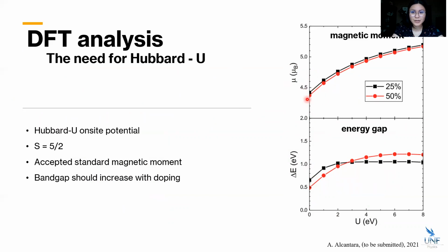So if we look at the magnetic moment, you can see that it is very low. And then as we apply Hubbard U, we have values of 0, 2, 4, 6, and 8. It raises up to the accepted value of a high spin state of 5/2. This is around 5.24 magnetons. And then for the energy gap, you can see that the 50% starts off lower than the 25%, which is not correct. And as we apply Hubbard U, it raises and it tapers off, and then this switch happens. So the system is still semiconductive, and that flip that is experimentally proven to happen shows.